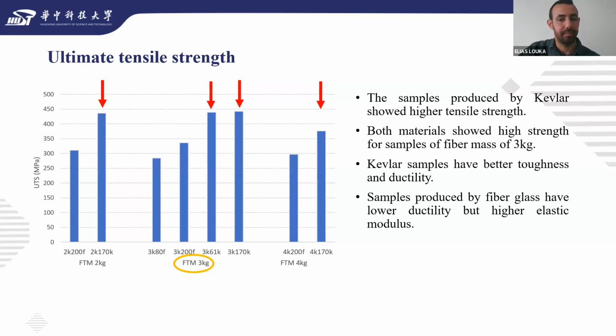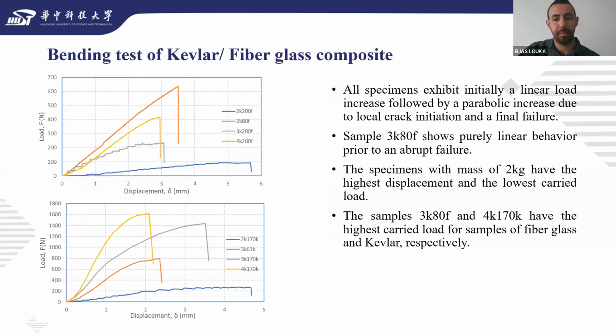Now we are moving to the bending test. Here we will find two curves of the load displacement of the composite materials with different fiber mass under bending load. The bending strength of the sample was calculated for maximum load and break. Generally, all specimens exhibit initially a linear load increase, followed by a parabolic increase due to local crack initiation and a final failure. As you can see, only the sample 3K80F showed purely linear behavior prior to an abrupt failure.